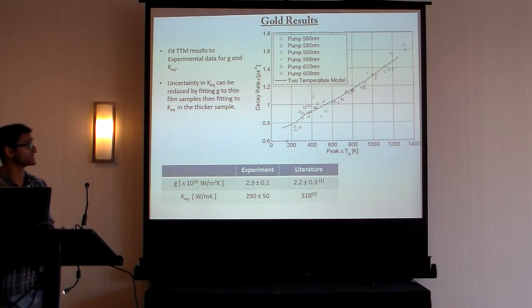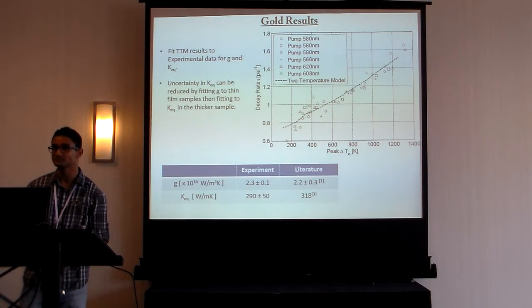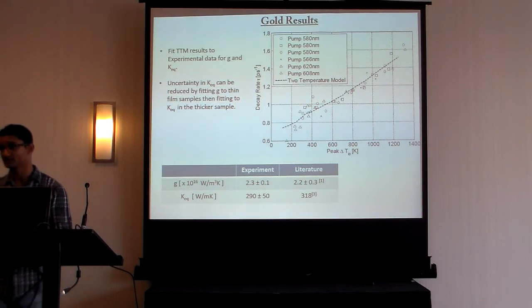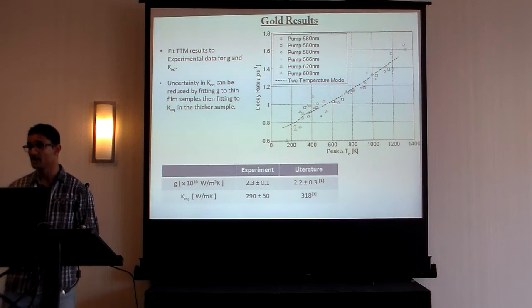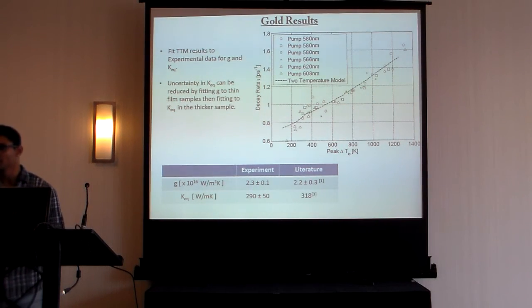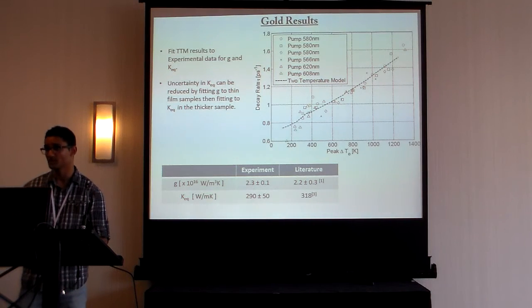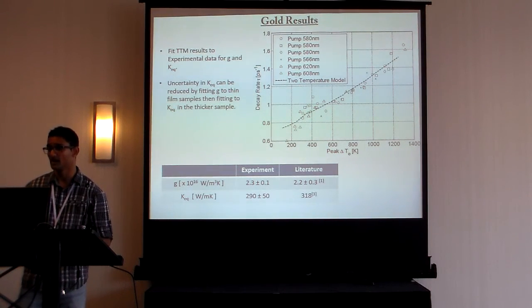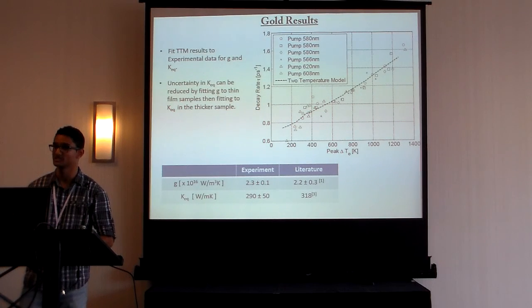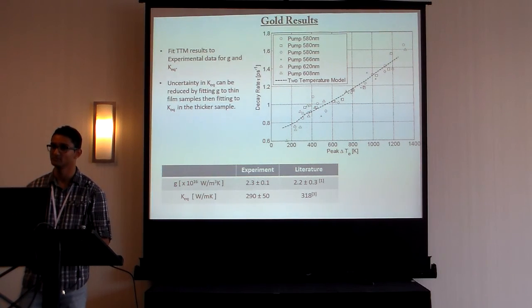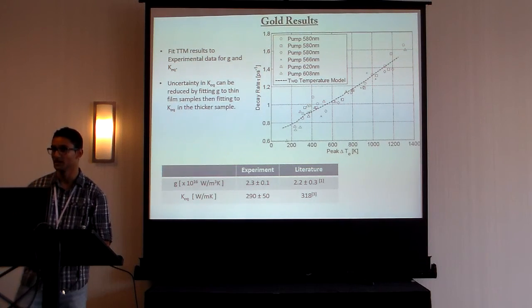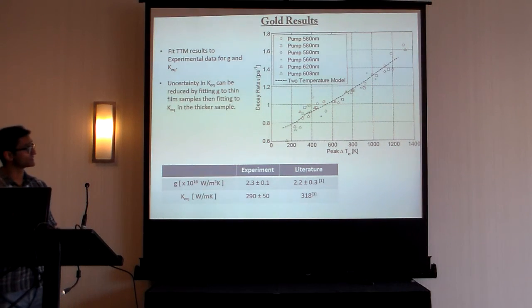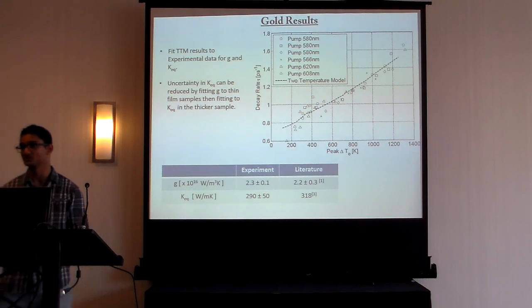There are actually many data points to which we're applying exponential fits, and because of the 1 picosecond thermalization time, which ranges from about 0.6 picoseconds to maybe 1 picosecond depending on the total power, we have to adjust the starting points of the fits, and that is something that we're looking into to remedy. But the small changes are most likely due to where we start our fits.